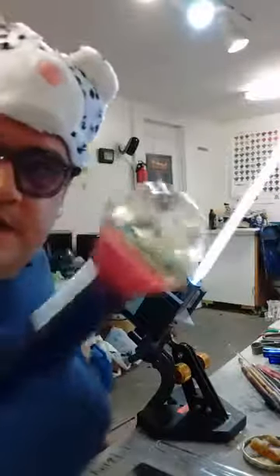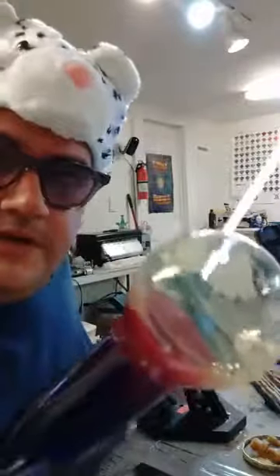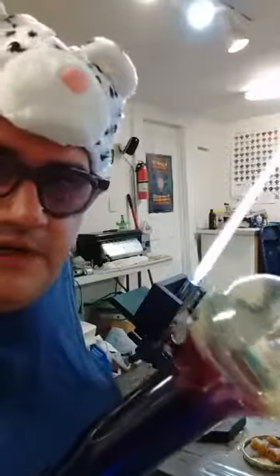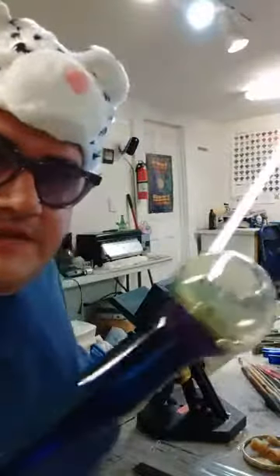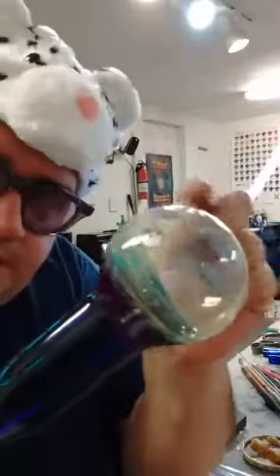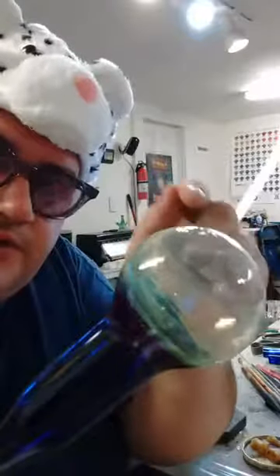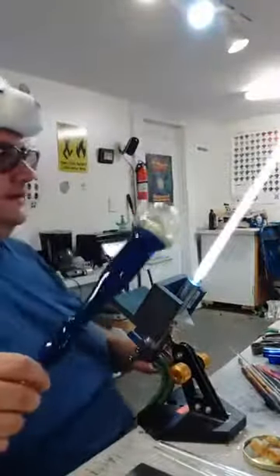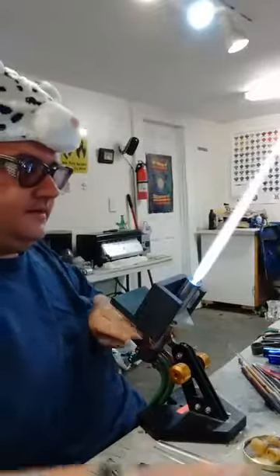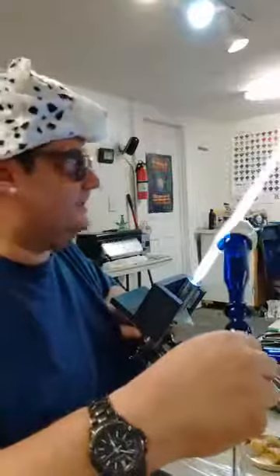So I'm going to start dotting this, and I usually dot with 3mm clear. You can use bigger rod if you want. I find that the size of the dots doesn't matter so much as the wall weight of this. If you want a nice deep honeycomb, make sure the wall weight on this is nice and thin. So, it takes a little while to dot these things.